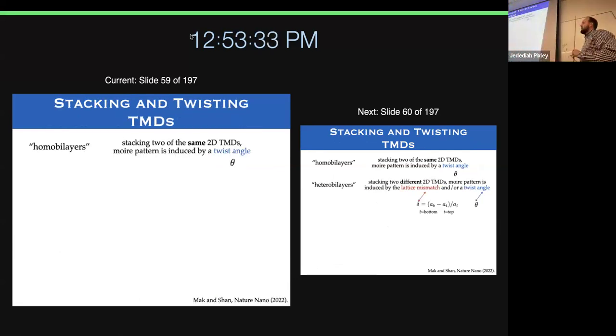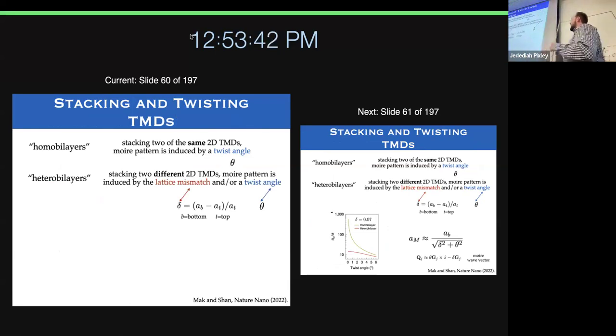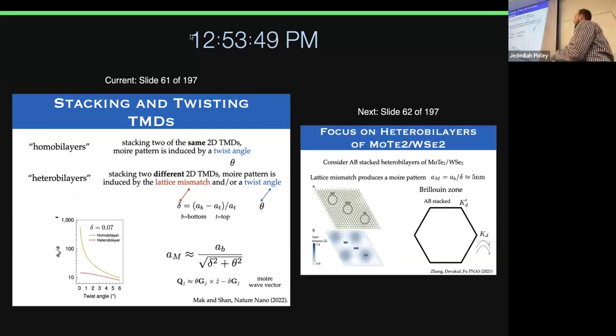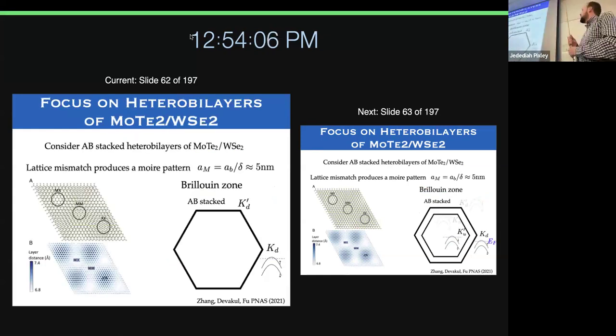Okay. So as I said, there are homobilayers. If I have two of the same material, I don't have a lattice mismatch, I just have a twist angle. But bringing in two different materials, the lattices do not have the same lattice constant, and there is a twist angle. And that also produces a moire pattern. So your moire length now is set by the lattice mismatch and the twist angle. And so in these heterobilayers, you can't basically get a massive moire scale. You just hope that it's big enough to get interesting phenomena. And in the case of what I'm talking about today, MoTe2 and WSe2, it's about a 5 nanometer moire pattern from that lattice mismatch, which is sufficient.